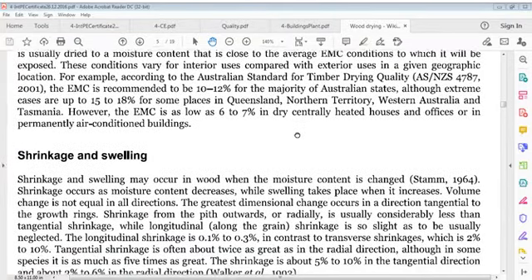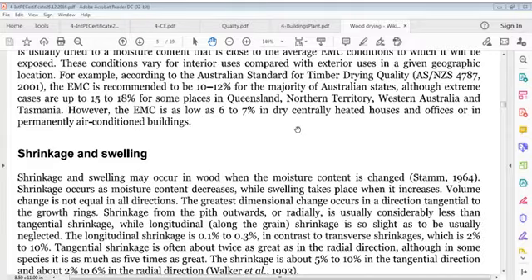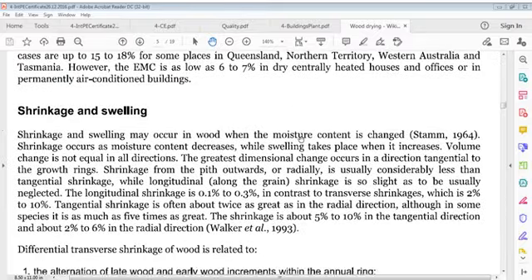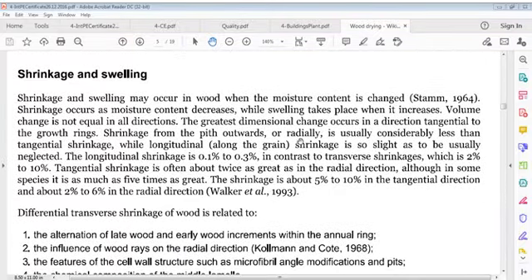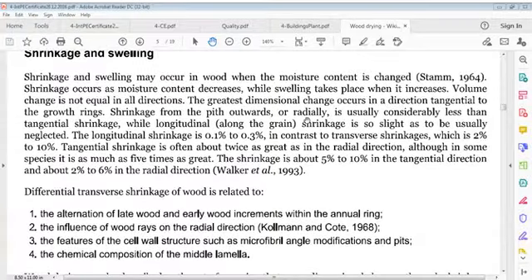For example, according to the Australian standard for timber drying quality, AS/NZS 4787-2001, EMC is recommended to be 10 to 12% for the majority of Australian states, although extreme cases are up to 15 to 18% for some places in Queensland, Northern Territory, Western Australia and Tasmania. However, EMC is as low as 6 to 7% in dry, centrally heated houses and offices or in permanently air-conditioned buildings.